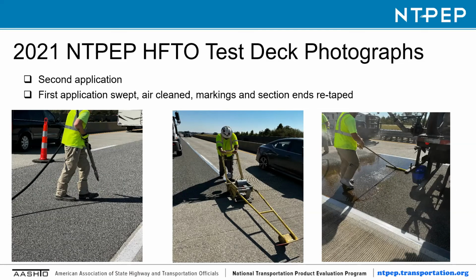As a rule of thumb, everyone needs to know that it takes almost double the binder to do a second application for a bridge deck because of the surface area of that, but it just nearly doubles the binder quantity for a second application. In the state of Tennessee, we'll let you know anything on concrete gets double layer from us because we do not want to have to go back out there on that concrete.